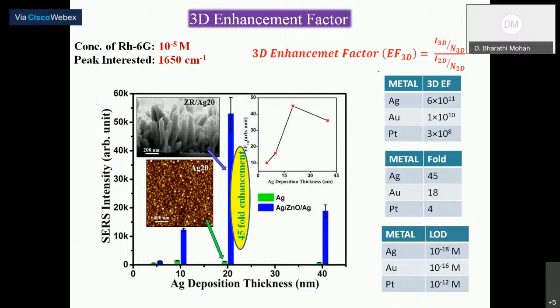We calculate the 3D enhancement factor and the 2D enhancement factor, from 2D and 3D substrates respectively, by preparing rhodamine 6G with a concentration of 10 power minus 5 molarity. And if you look at the enhancement factor in case of a 3D hybrid structure, it is 45-fold. And that is observed in case of silver-based structure. Whereas in case of gold and platinum, it is about 18 and 4 respectively.